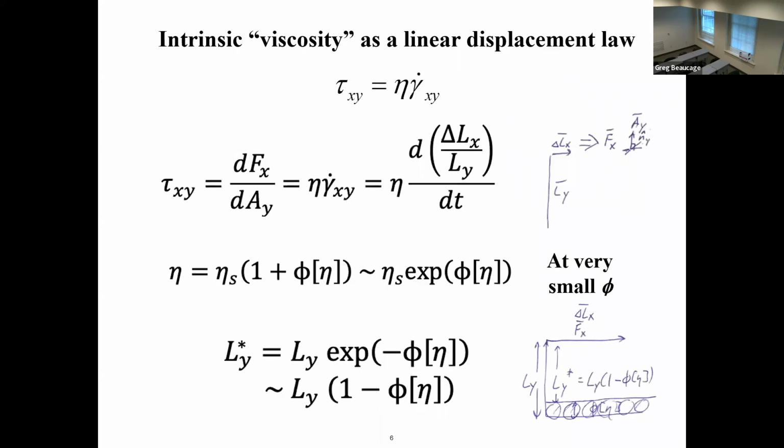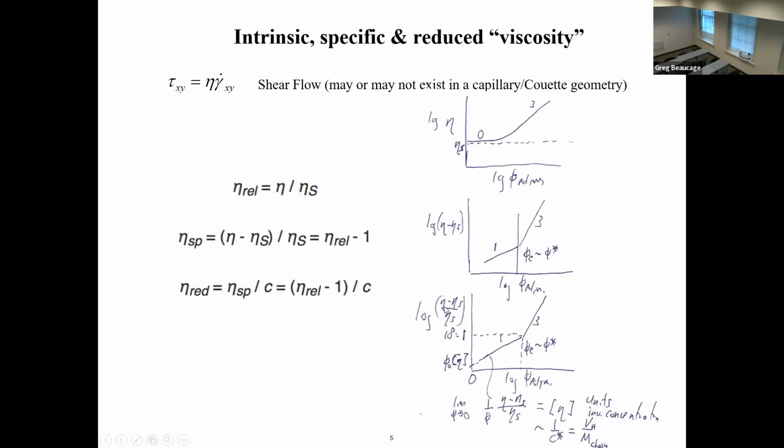at low concentrations. So this business of the intrinsic is like you take the viscosity minus the solvent, and that will let this Zimm behavior appear in concentration. And then if you normalize by the solvent viscosity, that becomes a unitless number. And when this number is at 1, that's where the transition to entangled shows up, as an unproven empirical observation. Right, so the 10 to the 0 on a log-log plot, and you look over and you see a transition in the slope, that's entanglement. That's the rheologist's definition of entanglement.